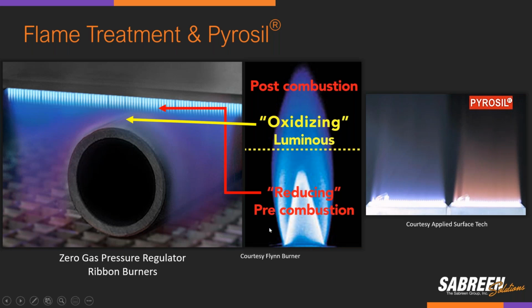I've identified several very important parts in the center section of the slide. Most often when I'm visiting clients, I see that the flame is not properly set up. The true flame parameters actually consist of an oxidizing zone highlighted in yellow, a reducing zone or pre-combustion, which is actually unburnt gas and has nothing to do with the actual oxidation process.